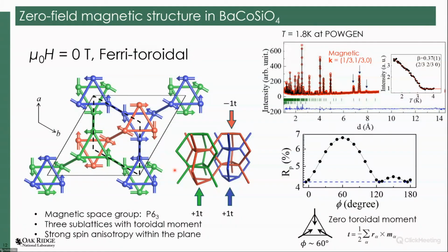We found there's actually a toroidal order in this system. To confirm its magnetic structure, since this is crystallography, those rotations have to be really meaningful, not random. We don't just stack some local minima. We try to define the universal spin rotation, then trace the rotation against the refinement quality. We found that all the minima connect to this kind of magnetic structure.